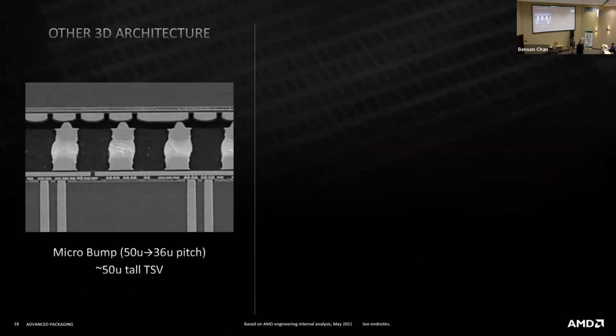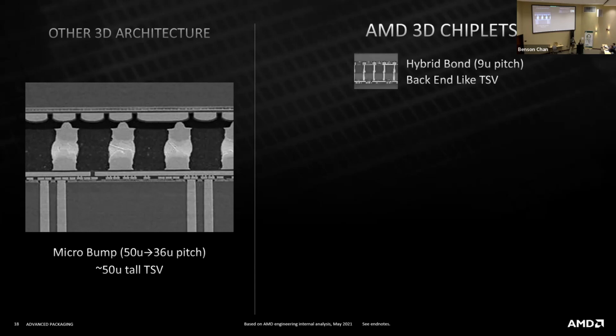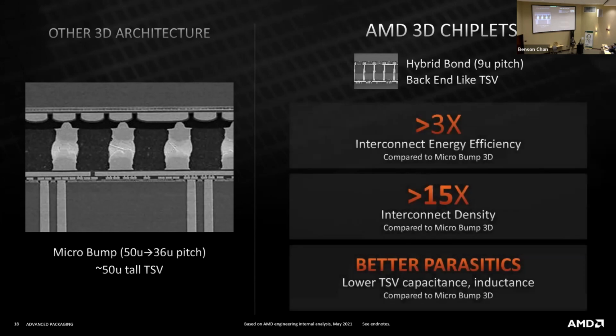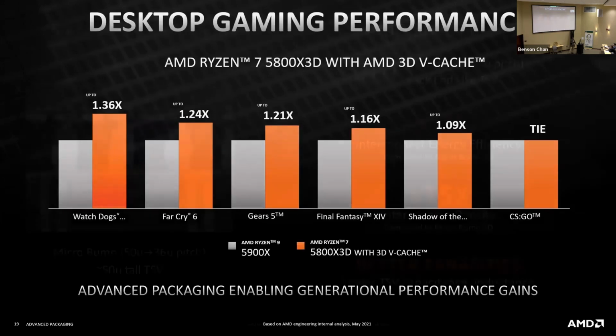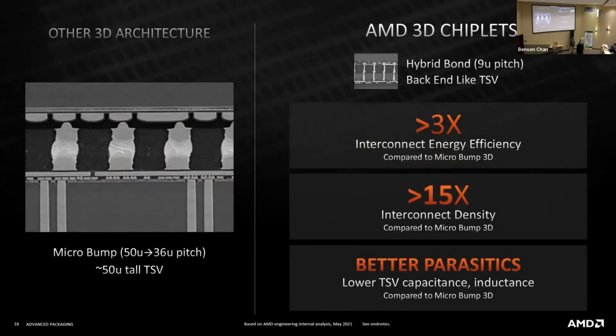So how does this compare to the industry standard? We've looked at some of the industry offerings on the previous page. A lot of them are microbump-based architectures, typically in the range of a 50 to 36 micron pitch so far, and maybe there is a little more room in scaling that pitch to perhaps 25 or so. But regardless, you're limited by the microbump. Compared to that, what we are offering in this hybrid bond, a 9 micron pitch, leads to a huge improvement in interconnect efficiency and interconnect density compared to a microbump, while offering better parasitics in terms of TSV inductance and capacitance.